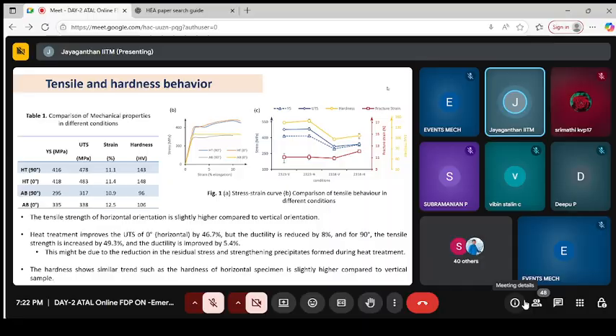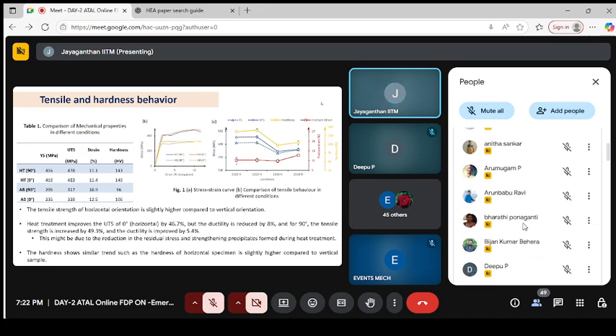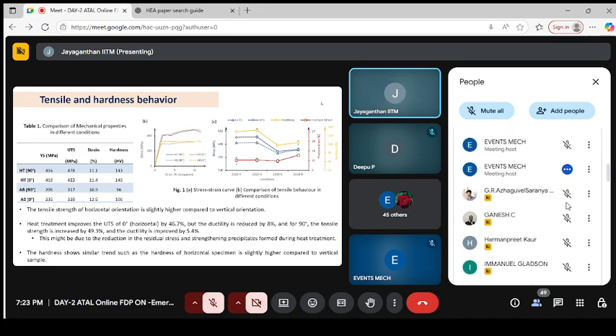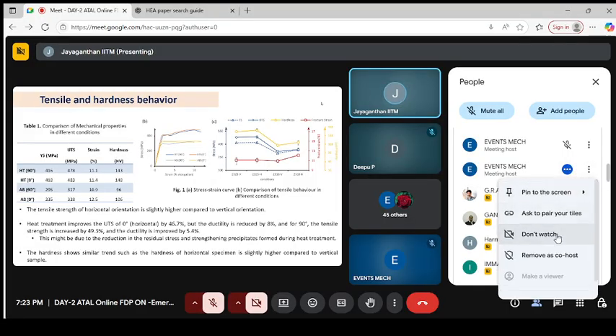Just to highlight what you see in this particular stress-strain curve, we want to highlight that AB is the as-built sample and HT is the heat-treated sample. What we want to highlight is the tensile strength and hardness. To generalize, the heat-treated sample provides better properties compared to the as-built sample, and both provide better properties compared to conventionally prepared material.